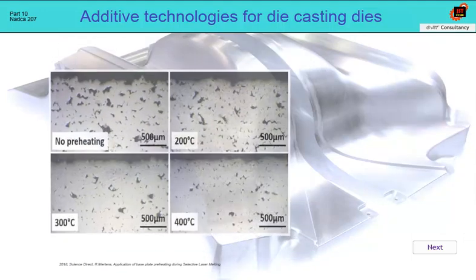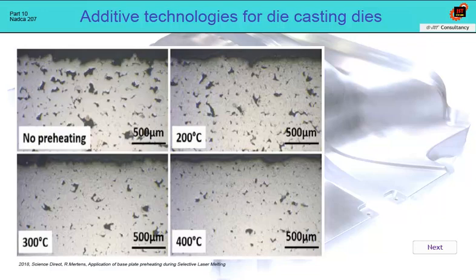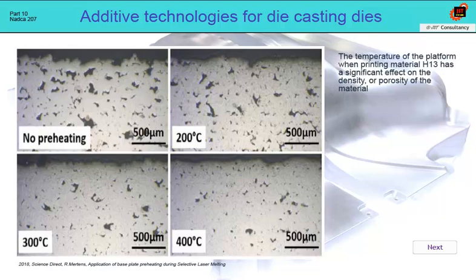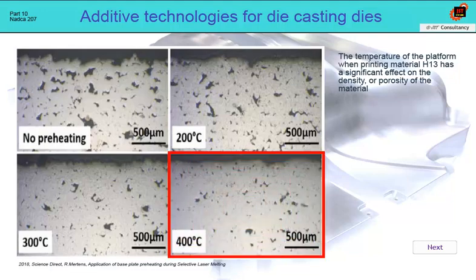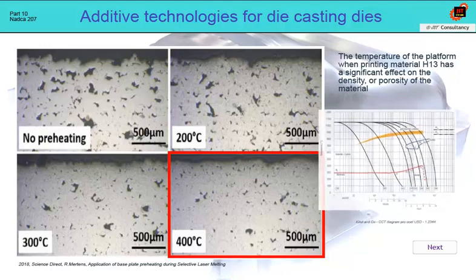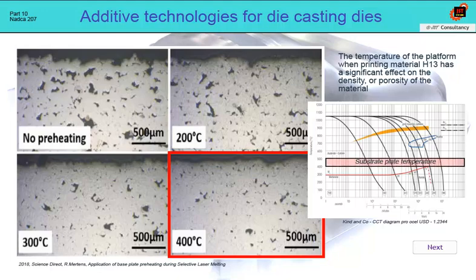A very important parameter for hot work steels of type H13, as well as for other carbon steels with martensitic transformation, is the temperature of the substrate plate. This has a significant effect not only on the internal stress, but also on the resulting density and structure. One of the reasons is that if we print at a temperature above the martensite start, one of the problems is reduced, which is the martensitic transformation in the initial stages of printing. It has been verified that if the platform temperature is 400 to 500 Celsius, then the applicability of this technology for hot work steels will be significantly improved.